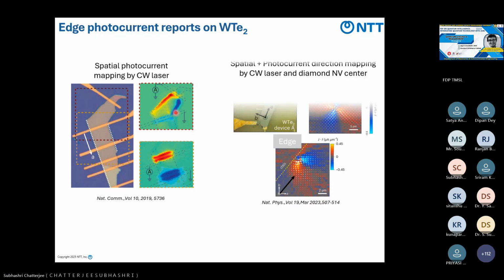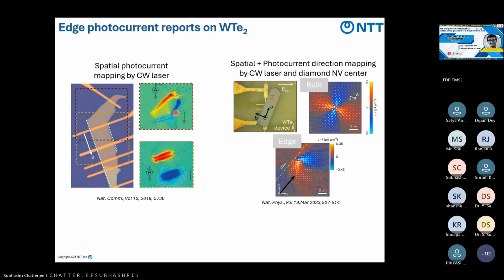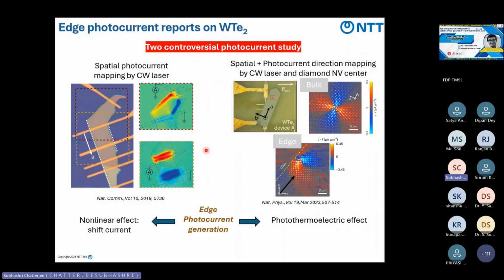Another paper used the NV center diamond quantum sensing technique with a CW laser, and by integrating spatial and photocurrent direction mapping, they said this is coming from the photothermoelectric effect, which creates a controversy. One side says this is a nonlinear shift current with potential for very fast sensing, the other says it's just a photothermoelectric effect.